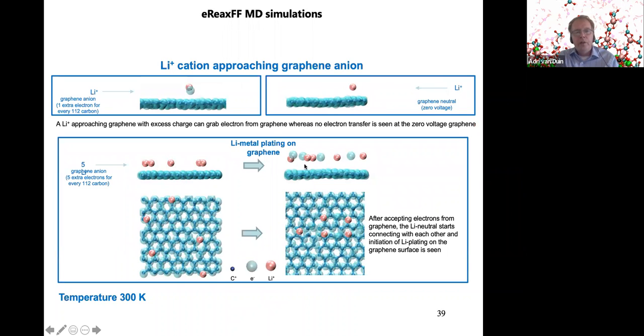This allows us to make a much better distinction between lithium cations and lithium metal. We can over time transfer electrons to lithium cations. Once the lithium cations become neutral lithiums, they can turn locally into a lithium metal that can plate. This is clearly something that can also be done reversibly. So this may be a concept that could be quite relevant for other 2D materials. We have now also developed this, for example, for various oxides and similar species.